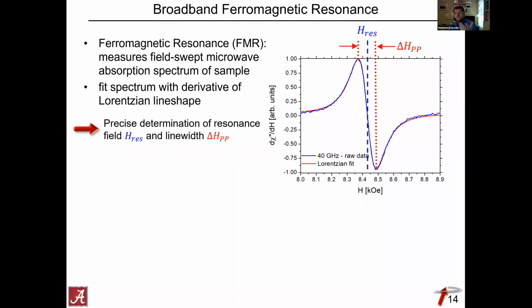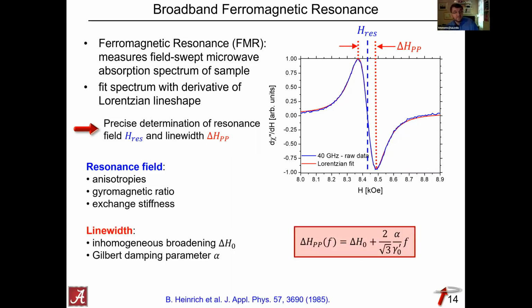So what you get from a measurement like this is, from this line shape, you can determine the resonance field itself and the peak-to-peak line widths. And as I mentioned earlier, the resonance field allows you to very precisely determine anisotropy. You can also determine the gyromagnetic ratio, in some cases the exchange stiffness, and a couple of other things if you try hard. The line widths, and this will be the focus of the remainder of the talk, allow you to learn something about the dissipation in the system. It also gives you some information about inhomogeneities in your sample, like the inhomogeneous broadening, delta H naught. And what most people are most interested in is this Gilbert damping parameter that enters the Landau-Lifshitz-Gilbert equation.